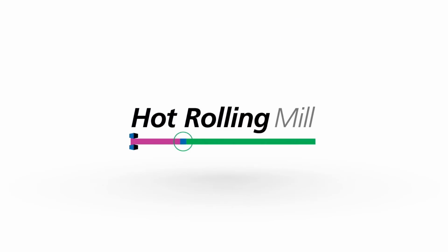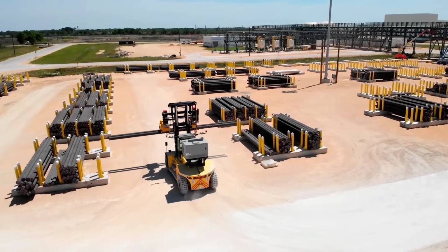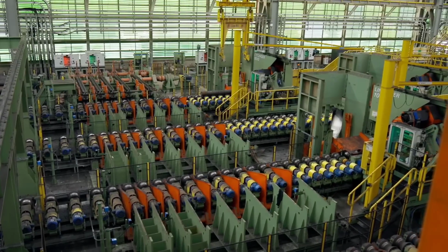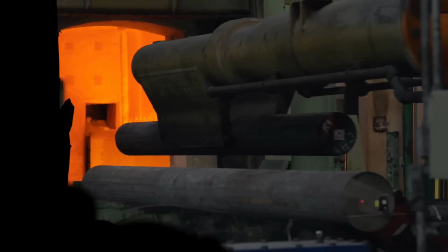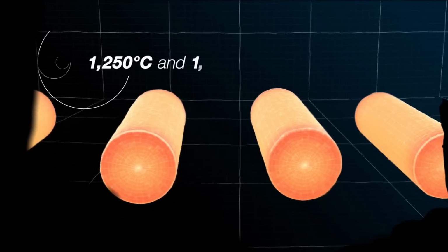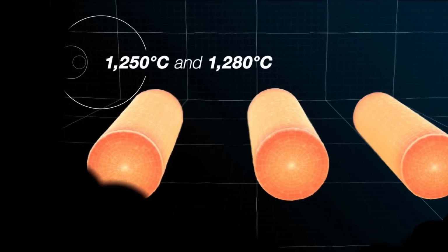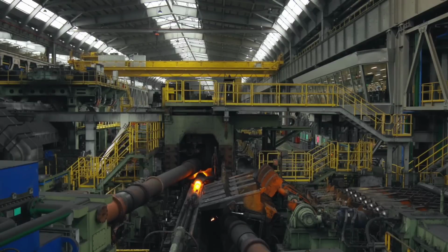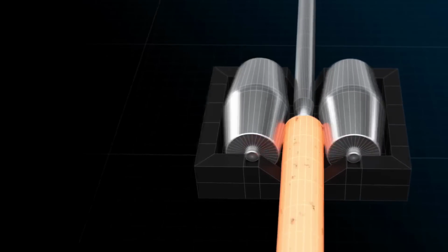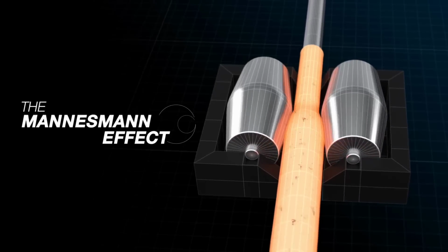The journey of creating a seamless pipe begins with solid steel bars, which are meticulously cut into billets of precise weight. These billets are then loaded into a natural gas-powered rotary hearth furnace and heated to a scorching temperature ranging from 1,250 to 1,280 degrees Celsius. The intense heat transforms the steel into a hollow bloom using a process known as the Mannesmann effect.